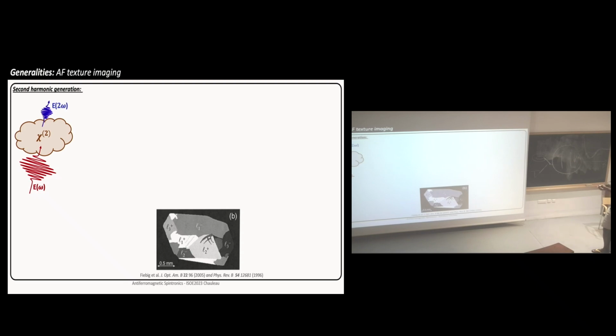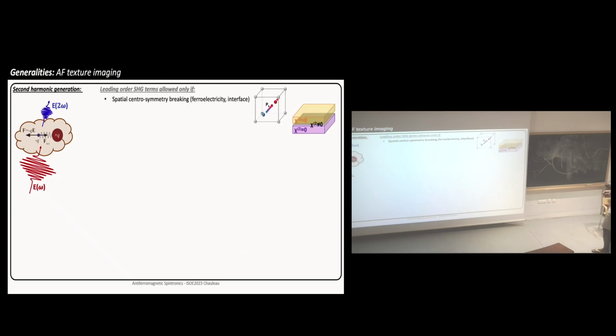Why is that? Because the principle of second harmonic generation is the following: you shine a light at omega on the system, which has some nonlinear susceptibilities, and it re-emits light at 2 omega, twice the frequency. Or in other words, at wavelength lambda and lambda over 2. At leading order, this is only allowed in non-centrosymmetric systems. So if you have a breaking of central symmetry, such as in ferroelectricity at an interface, it's very efficient to do this. But okay, that was the normal way we discussed SHG last week.